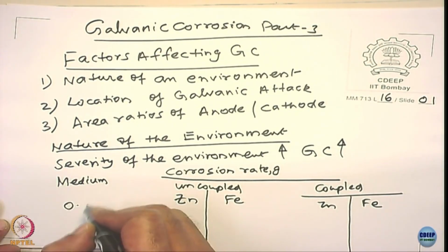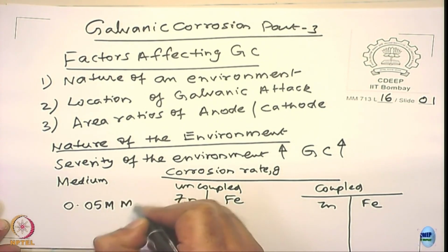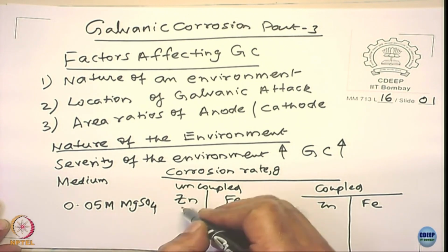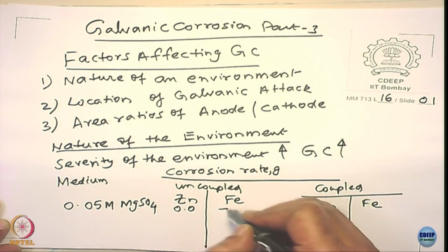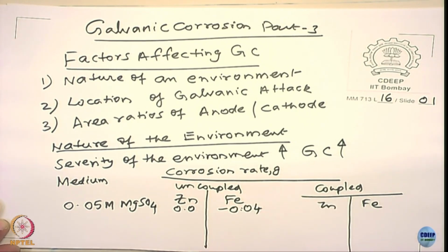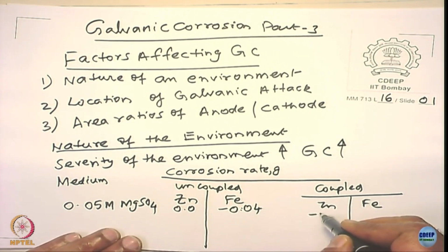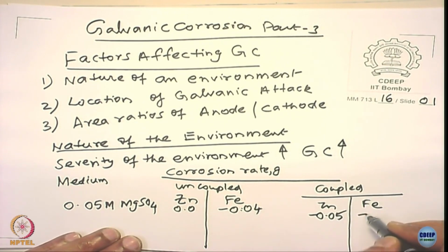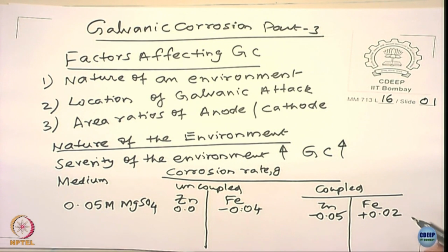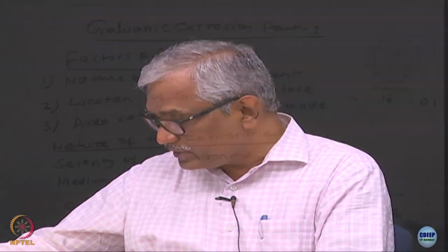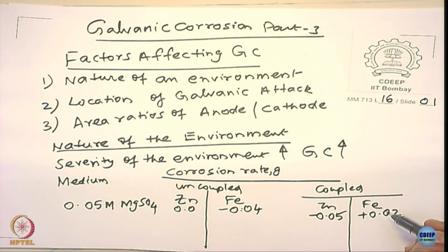Let's take the case of 0.05 molar magnesium sulfate. Zinc virtually does not dissolve and corrode; steel corrodes. When you galvanically couple these two, you notice that zinc corrodes at a higher rate and steel in fact shows a marginal improvement in the weight, in fact a weight gain. But the weight gain is not because of growth of steel, growth of iron. It primarily happens because when you make a metal cathode, the pH goes up and some deposition occurs. So if you clean them up, you would not see any significant increase in the corrosion rate. This rise in weight is not related to metal deposition here.